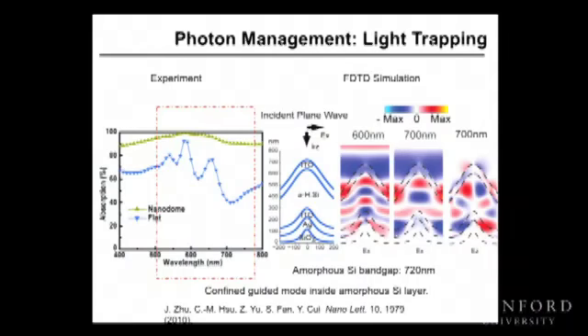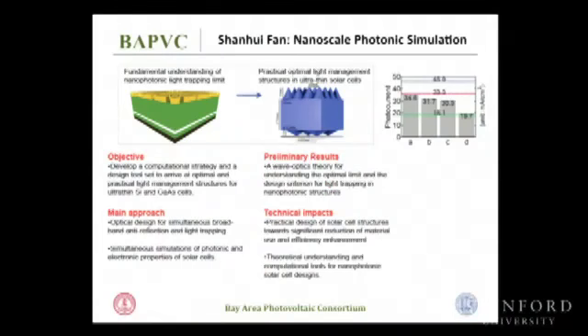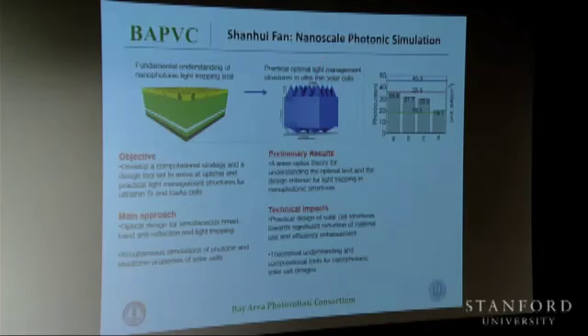And this type of idea, over the years, we extended into the consortium research. We found a project by Professor Shanhui Fan using nanophotonic simulation to see whether it's possible to use very, very thin silicon to absorb all the above bandgap photons. Here's a schematic drawing. This is only 2 micron thick silicon. Typically, you need 150 micron to absorb all the light. Now, this is only 2 micron. Using this double cone structure, this is the front cone with light coming in from the top, and this is the backside cone. They have different diameters. And the front cone allows you to get the sunlight in without reflection.